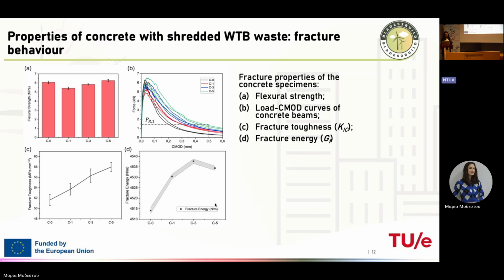But mostly we observe that increasing wind turbine blade waste enhances ductility and bridges cracks. And what we can see at the curves is that despite reduced stiffness, we have increasing residual flexural strength. This is the green lines for dosage 5% at graph B. So it's like 2.5 times higher than for the control sample.